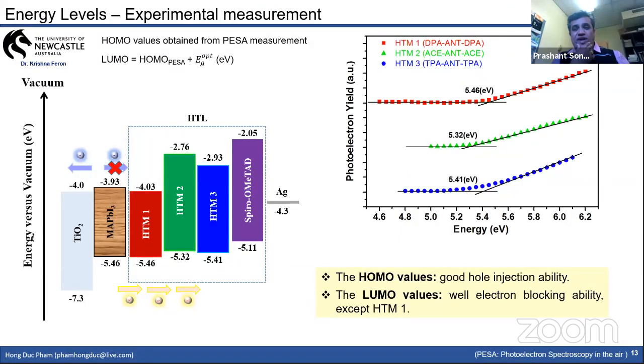And looking at these compounds and their energy levels, usually to calculate the HOMO energy level, there are various techniques people use. Cyclic voltammetry is one of the very common and low cost techniques, where the HOMO-LUMO values can be determined by oxidation and reduction onsets. But again, in the case of cyclic voltammetry, the biggest drawback is that your material needs to be dissolved in a solution, and then you get those values. Sometimes those values in solution might not be relevant to the actual device, where the material is in a solid state. So the technique called photoelectron spectroscopy in air is a very straightforward and nice technique. I was fortunate enough to get knowledge of those types of techniques when I was